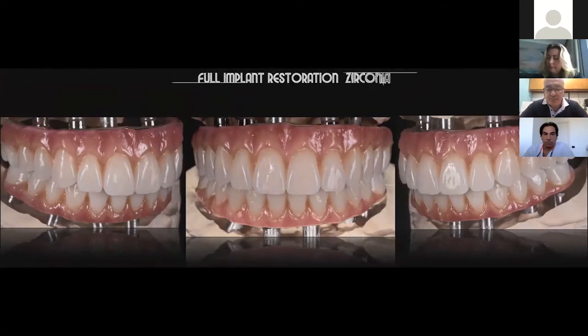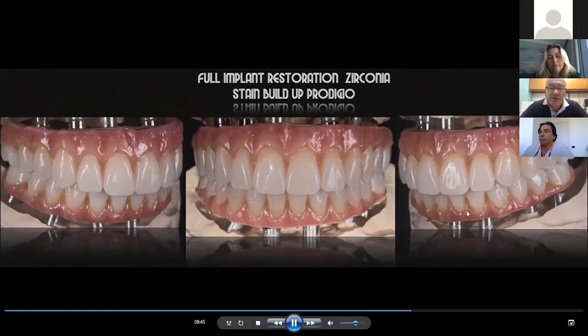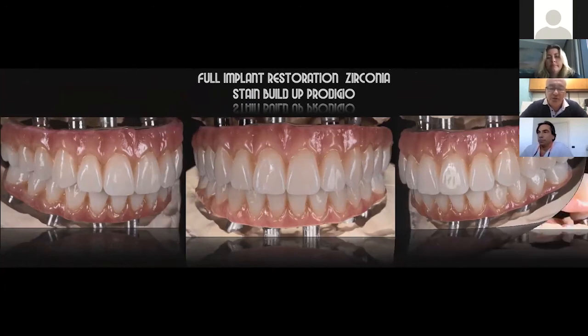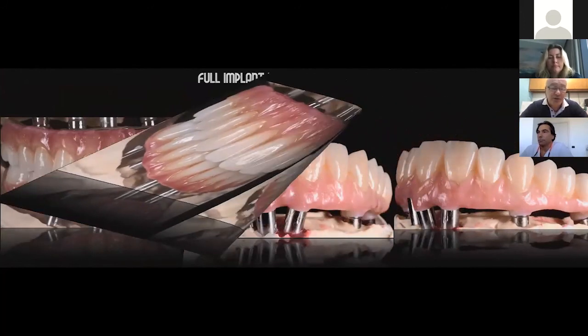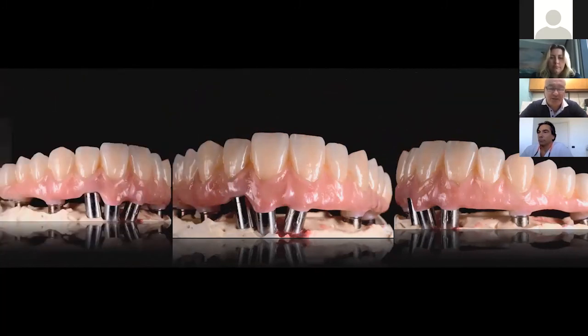This is another upper and lower implant case where you see the texture that you can really play with. All of this texture that you can see in this area around the tooth with the pink, you can really play with the Prodigio stain buildup, and you can control it with that material in any direction you want. You can create a texture, and you will have exactly the same texture after you bake that you had before you bake.